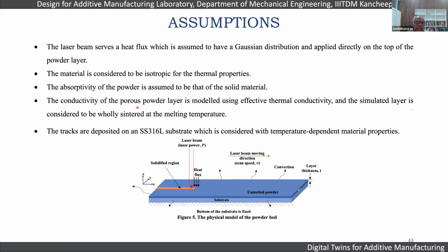So we made certain assumptions here. We use the laser beam as a heat flux with a Gaussian distribution, and the material we have considered isotropic, for simplicity. And absorptivity is considered to be the same as that of the solid material. As I said, the absorptivity of the powder we calculate from the particle dynamics, and then we created an equivalent absorptivity, which corresponds to the same solid material.